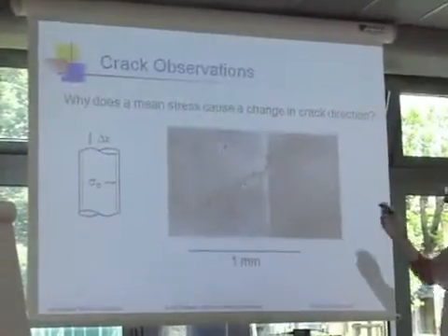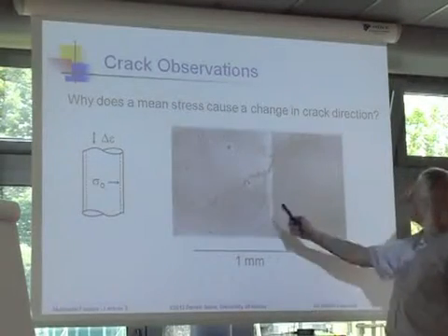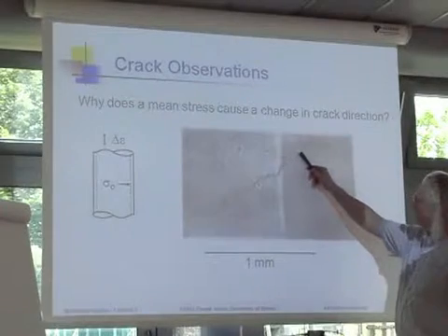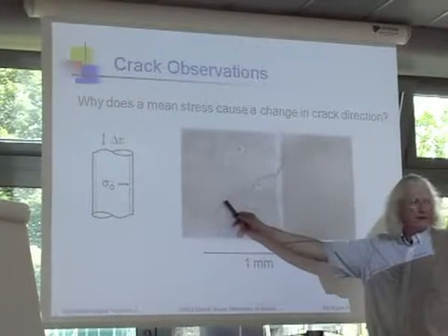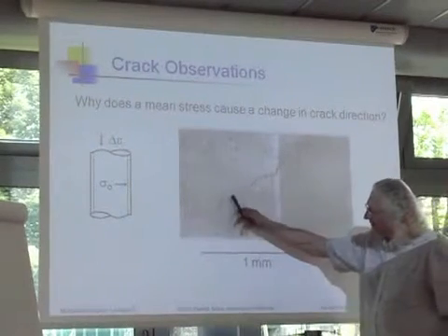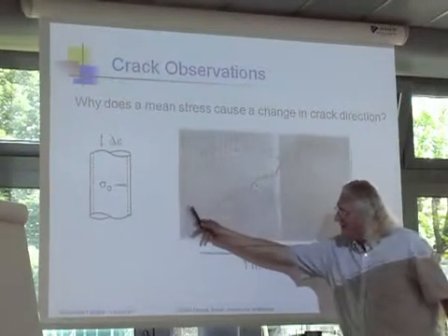Look, here's what happens. Right? I mean, you are right. Look, at the beginning of the test, right, the crack grows more or less in shear. Okay? After a little while, the crack turns to grow in tension.